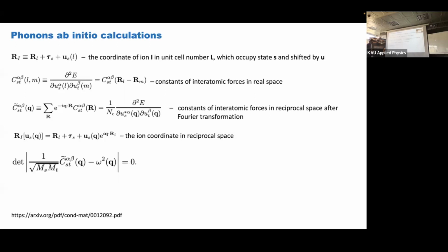It is called density functional perturbation theory, because we distort our crystals with very small distortions. They are very small, that's why we have to calculate very precisely. That's why we have to relax our structures to 10^-8, for example, precision for forces, because these distortions are very small, and if you have huge forces acting on the ions, you will just not see anything. So it's better for ions to be in an equilibrium state.